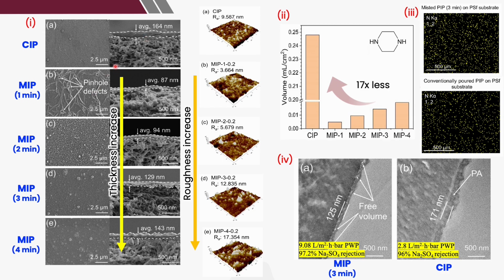So these are some of the key results we obtained from our experiment. CIP here means conventional IP process. MIP means the misting IP process. 1, 2, 3, 4 minutes here means the duration of the misting time. If you look here, the misting time actually is very important. If you mist the membrane too short, like 1 minute, you have a lot of pinholes. This means that the membrane does not have sufficient monomer to form the polyamide layer. By increasing the misting time, you can see the thickness of the polyamide layer increases. It means that you have more monomer to react with each other, and a thicker polyamide layer can be formed.